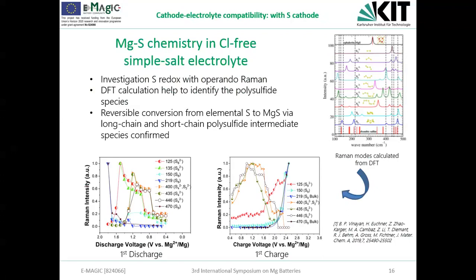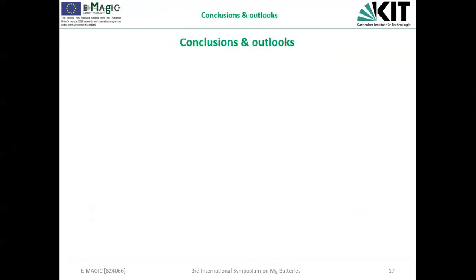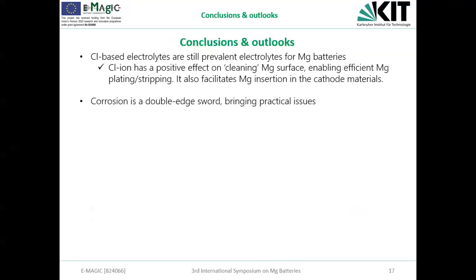In principle, we have a reversible conversion from elemental sulfur through the long chain and short chain polysulfide intermediate species, and it ends up with magnesium sulfide at lower voltages. This reaction mechanism is quite similar to what we have investigated before by using the chlorine-based electrolyte. So this also means that our electrolyte is compatible with the sulfur cathode.